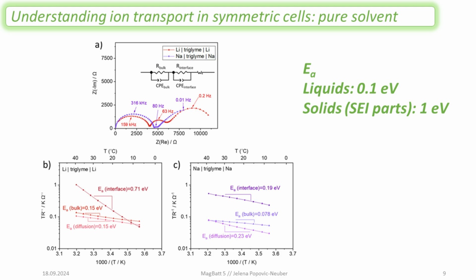But there has not been any direct evidence that there are space charge zones in the SEI. We have never measured it. So since the mid-90s, as a kind of red thread throughout, the SEI is a special material. Each component is not particularly conductive, but for whichever reason, it's a very conductive material.